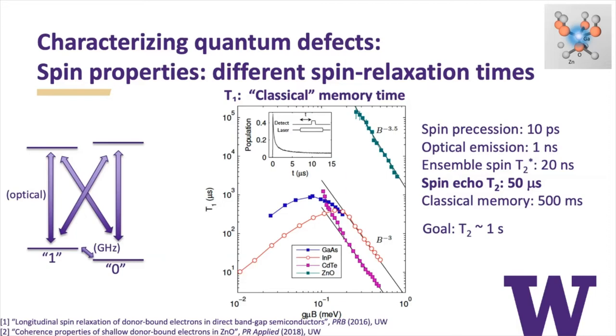Right now, superconducting qubits are around 50 microseconds, and now the record is around 300 microseconds. Because we have cases where defects are exhibiting very, very long coherence times, this is in silicon, mainly in silicon and diamond and silicon carbide, so materials that can be made very, very pure, it's pretty safe to say that people don't get really excited unless there is a possibility to get to seconds eventually. So we really want to be in the second time scale, and of course longer eventually.